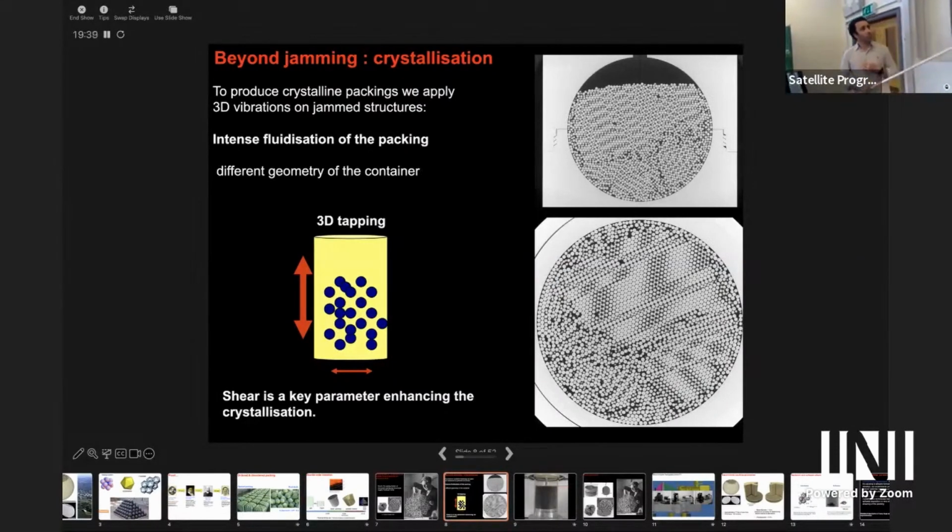However, following this protocol, we were able to create structures that certainly showed some order. Okay, so this is the cross-section of a spherical packing. And this is another cross-section perpendicular to that one. As you can see, there are ordered regions here and there. There are some seemingly disordered parts as well. But overall, we achieve a packing density that is greater than Bernal's density, but still lower than a fully crystal packing.